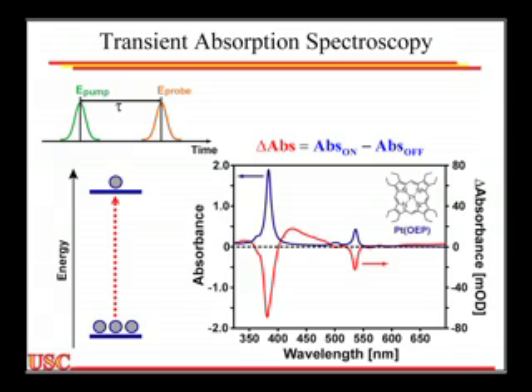So let's say that I've got PTOEP. What I'm showing in blue is the linear absorbance spectrum. There's my Soret band and my Q band. So I bring in a pump pulse, and at some time t equals 0, I pump it up into its excited state. So I depopulate the ground state. I used to have 3 ground state molecules, now I've only got 1. And so if I take the difference spectrum between the t equals 0 spectrum and the t equals tau spectrum, I wind up generating the transient spectrum.